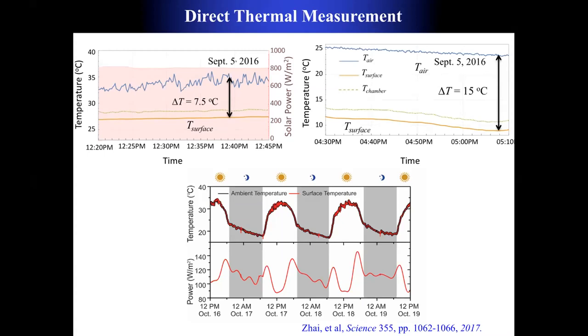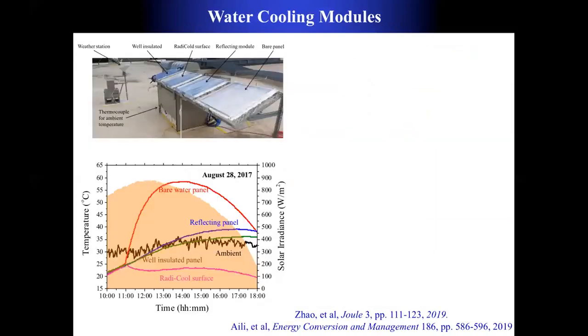In the meantime, if we tell people this is cooling, people will say, okay, that's not too exciting, right? Because people have been using so-called reflecting materials. We also try to insulate things to make them not as hot under the sun. So we made an experiment like this one, with a lot of panels with water inside. We try to directly show people we have a material better than just reflecting the sunlight, or better than well-insulated walls. You can see here, we have ambient temperature and different panels. The best material we have is our surface. You can have about 10 degrees C lower than ambient temperature if you have water inside.